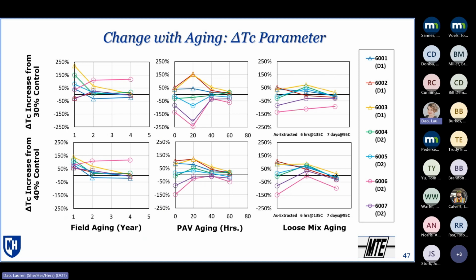The first set of figures show you the field aging. So you can see, again, the trend that you saw with the bars, but you're seeing it quantified here, that initially a pretty wide range, but as we're seeing the field aging, these are coming closer together and getting closer to both the control values. The PAV aging, again, remember, this is the as produced material extracted and recovered, and then 20, 40, and 60 hours of PAV aging.